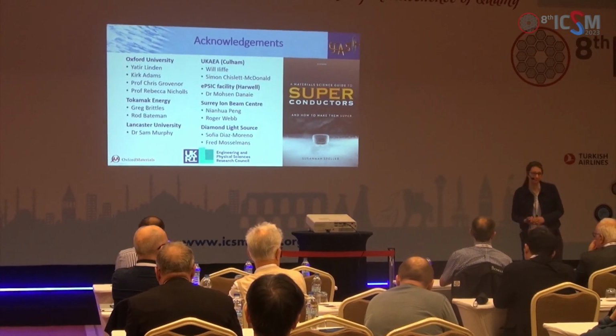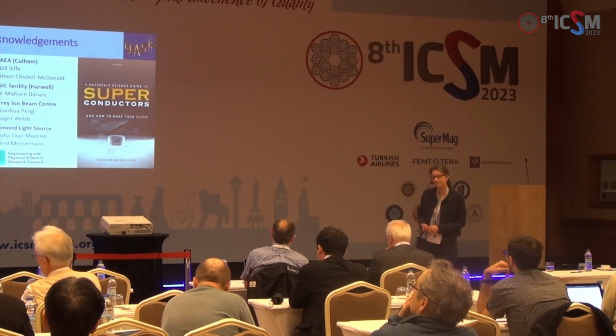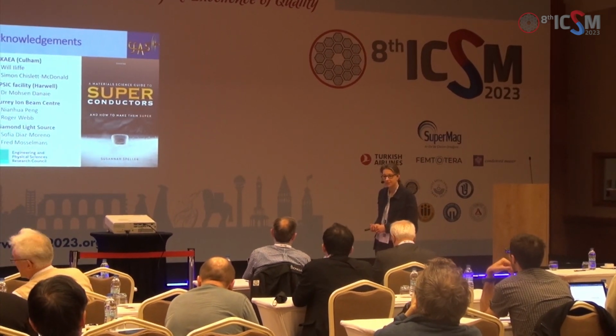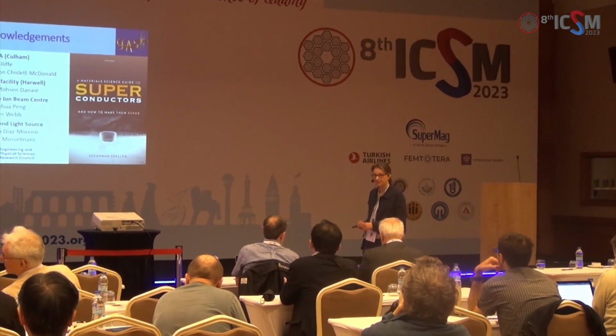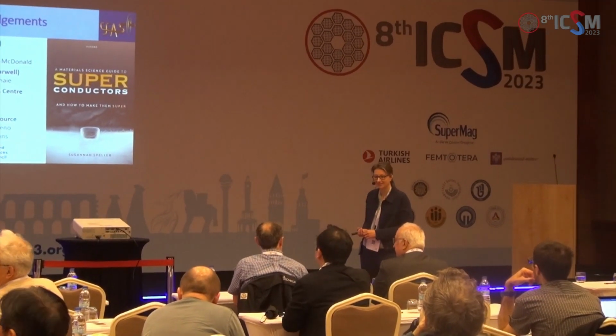Thanks. When you're considering the annealing and recovery of TC, of course, an optimized TC requires an optimization of the oxygen stoichiometry. And that usually requires oxygen at high temperatures. So how do you take this into account compared to your experiments to recover TC? So when we do the annealing, if we're going above room temperature, if you just did it in air or another environment, you would pull out the oxygen, and yes, you would decrease TC. So those annealing experiments are done in oxygen to stop that happening. For the room temperature anneal, we don't do that because at room temperature the oxygen's not very mobile, so it doesn't get pulled out at a very fast rate.